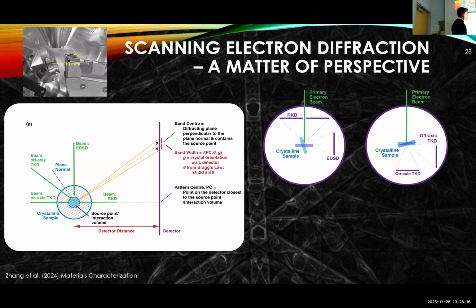In Tianbi's PhD, we've actually done a series of different setups. So this is in a reflection pair of geometries. You have EBSD in the blue with the sample tilted towards the detector. Coming in December, we'll have EBSD running in flat configuration, so no tilting of the sample. And we now have a large backscatter pixelated detector quad pair called RKD around the pole piece. We can also set our SEM up as a TEM, and we can set up an electron transparent film, and we can use an on-axis TKD detector. So we put the EBSD detector below the sample, or we can run a regular EBSD detector, but just move our sample upwards with regards to the detector, the so-called off-axis geometry.